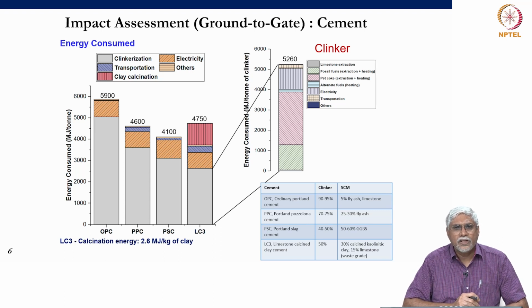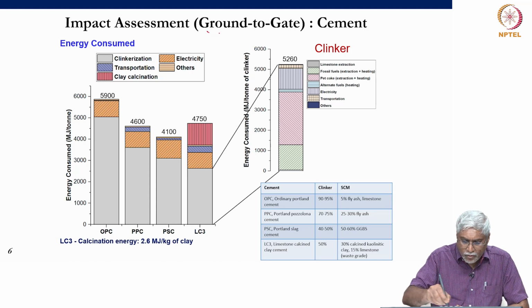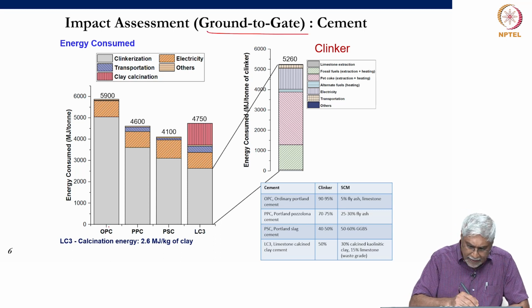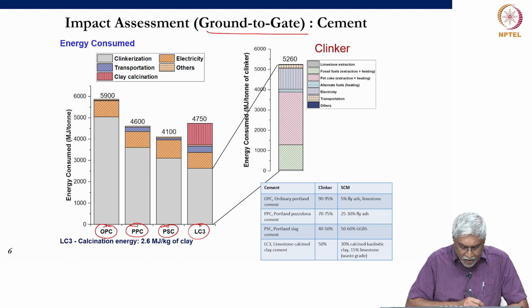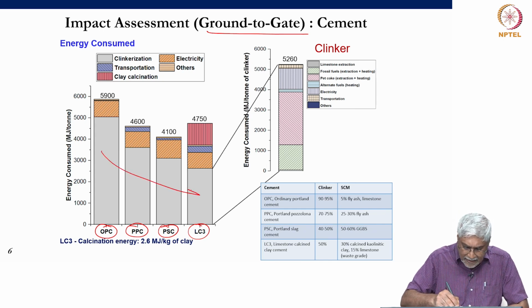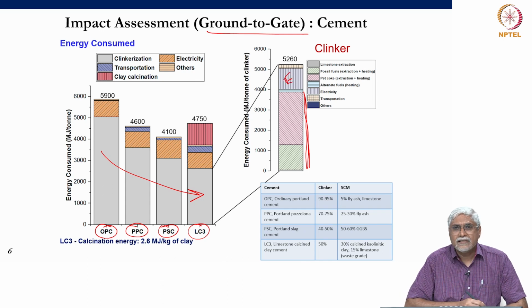Similarly, we can look at the energy consumed or the embodied energy. This is again for a ground to gate system, and I am looking at the 4 different cements that I just discussed: ordinary Portland cement, Portland pozzolana cement. So, the PPC has fly ash, PSC has slag, and the LC3 has calcined clay and limestone powder. Again, the grey part is coming from the clinker, and in the clinker the embodied energy is mostly coming from the fossil fuels, pet coke and other fossil fuels, and the electricity. Electricity also is used a lot. So, that has its own embodied energy content for the production of electricity, not just the electricity itself, but the embodied energy of the electricity.